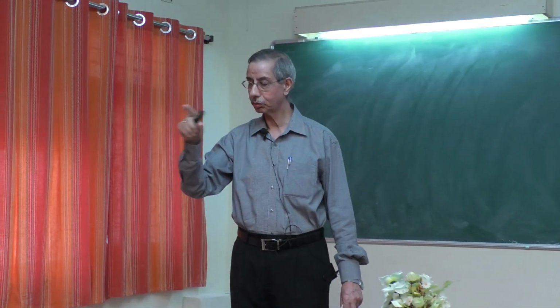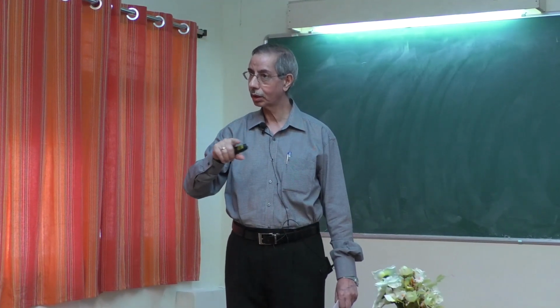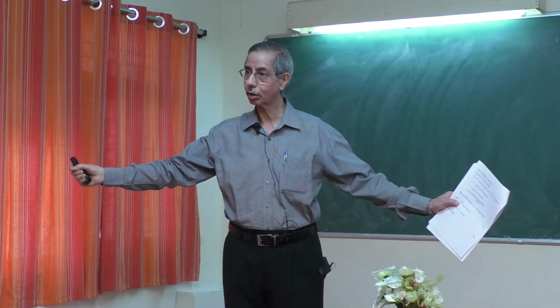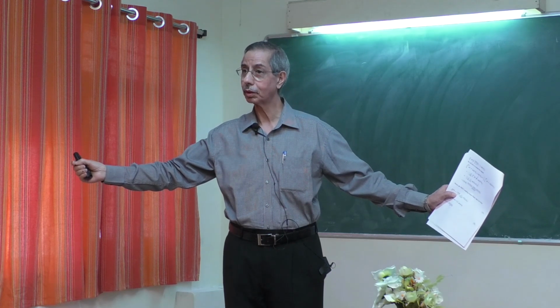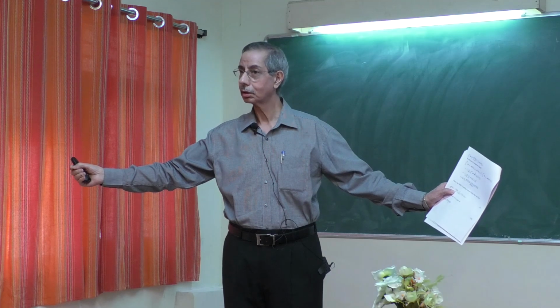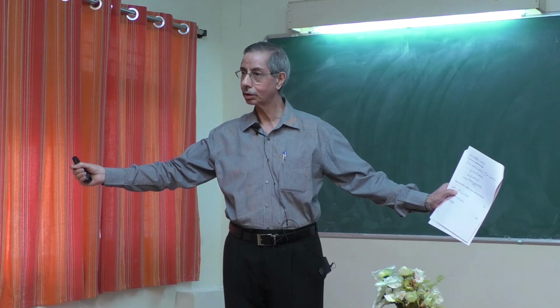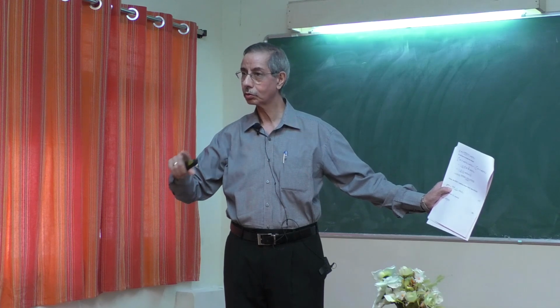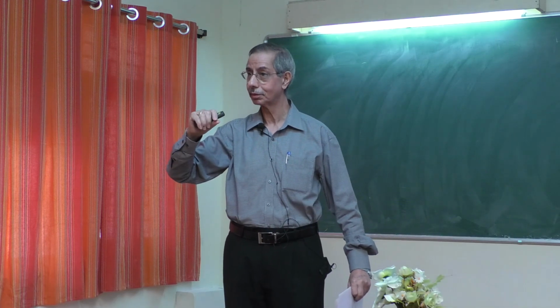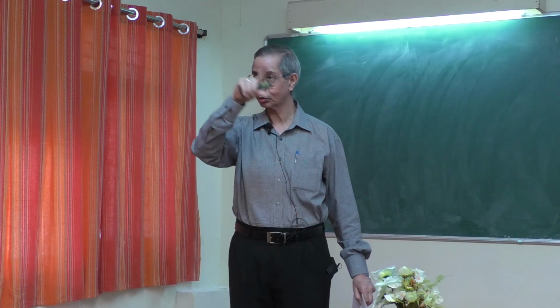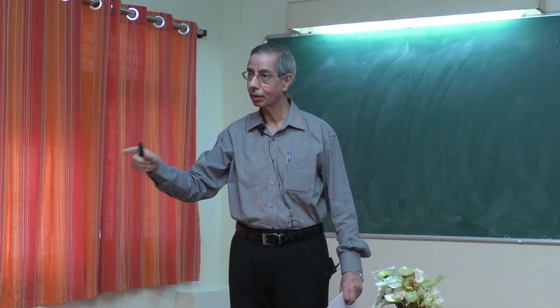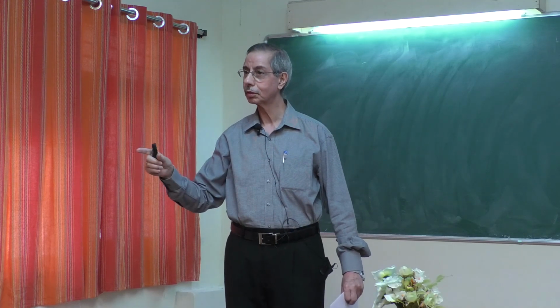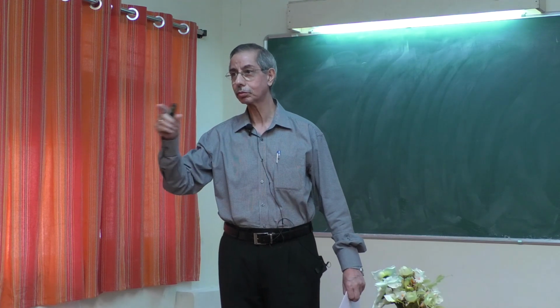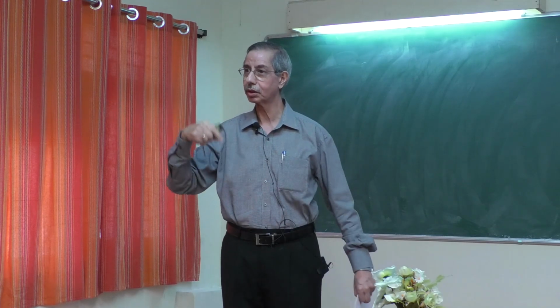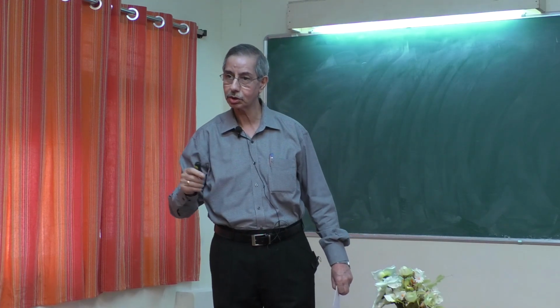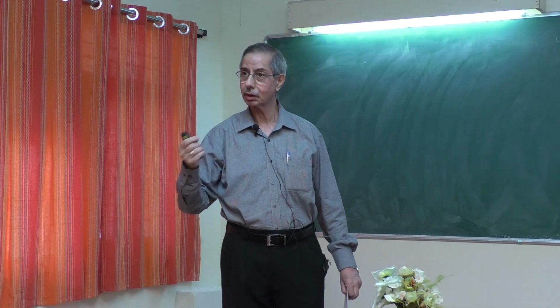But there, between the 4f localized moments, the distance is too large for any overlap of the 4f wave functions. So hence, there is no possibility of direct exchange coupling the 4f spins in gadolinium. It is operating through the conduction electrons of gadolinium itself, because there is no other system. So conduction electrons of gadolinium are mediating magnetic interactions between the 4f moments, and because of the distance between them, it prefers a ferromagnetic order in the system. So that's how ferromagnetism is stabilized in gadolinium.